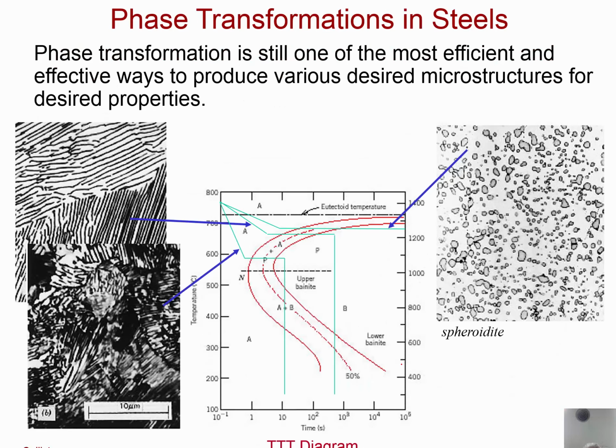Again, these are some pictures we talked about of phase transformations in steels. You get these structures. This would be a coarse pearlite. This would be a fine pearlite. And in both cases, a good question to ask yourself is what is the carbon content approximately in each case? And you should answer it's about 0.8% carbon. That's fully pearlitic, which means you had austenite that you'd quench down.